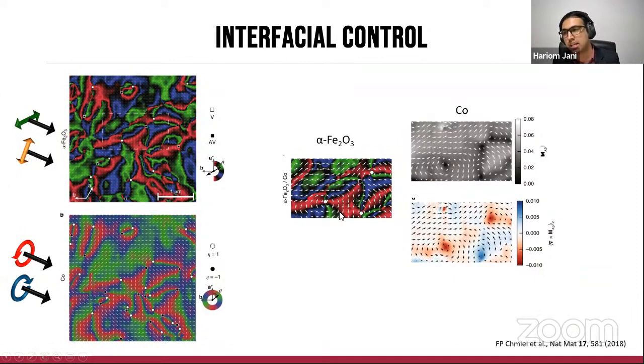Now, the arrows can be actually used because cobalt is a ferromagnet, and we can use angle-dependent mapping to create these cobalt maps. And if we analyze the magnitude of the XY component of the cobalt, we can clearly see that the value remains almost constant away from the cores. As you approach the core, suddenly the XY components diminish, and because of the preservation of the length of the magnetic moment, it would imply that the cores would actually be out of plane, either up or down.